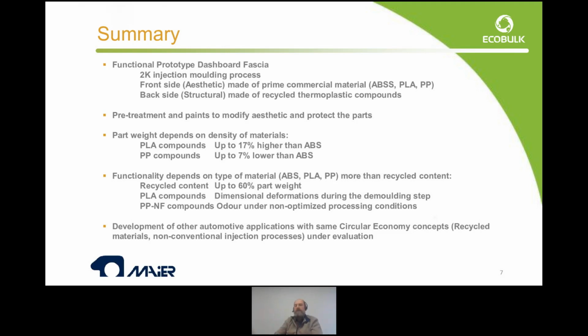The most important point to remark is, well, we can use up to 60% of recycled material to produce a functional component, but we detect some issues depending not on the amount of recycled content, but on the kind. For example, if we try to produce a component with a PP modified with natural fiber, due to the presence of the natural fiber, those materials tend to produce some odor if you are not very careful during the injection process. On the other hand, PLA compounds seem to work properly, but you have to be careful to control the potential dimensional deformations on the final parts during the molding operations.